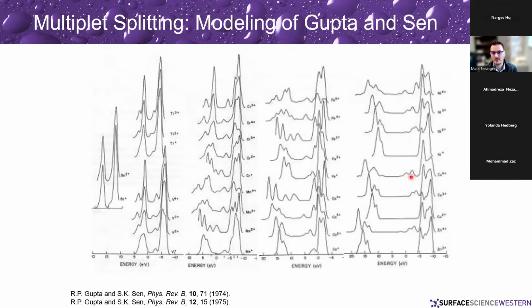And this was predicted many years ago, some of the work by Gupta and Sen, where they modeled what this kind of multiplet structure would look like for all the different transition metals. You can see that they're not nice sharp single peaks. All these things show up as multiplet peaks. And so this can get very confusing very quickly, particularly when you have even databases such as the NIST database saying, okay, you have a single binding energy for chromium-3 oxide, even though you've got a peak that has all this structure to it. So which peak does that refer to?